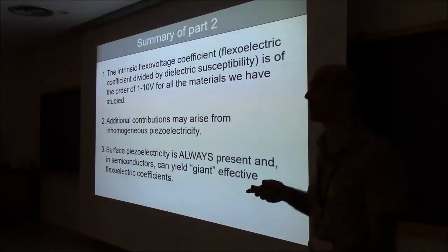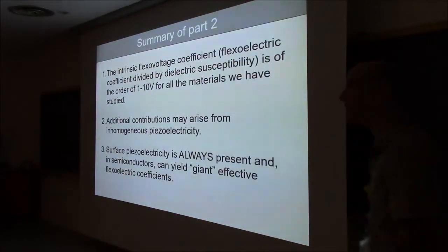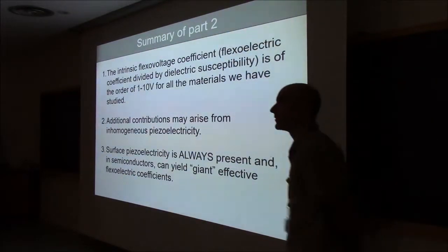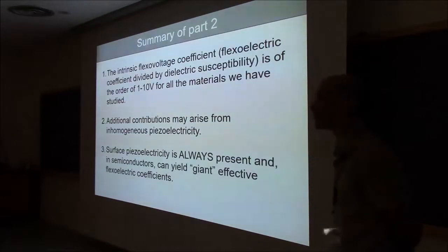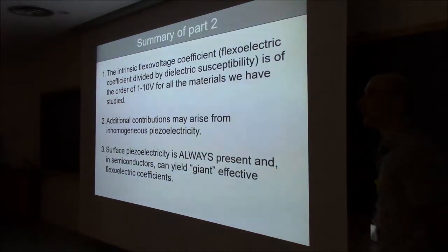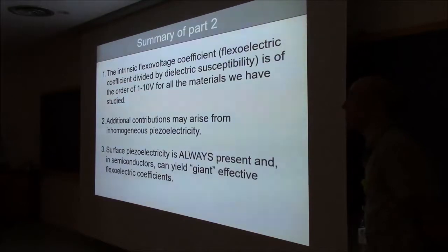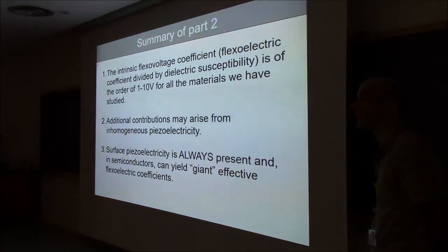Has the same been done for STO, like where you make oxygen vacancies to make it more conducting in the center? I have not done it, but there's no reason why it shouldn't work. In theory, you can just put it in the oven and see what happens. I mean, if it works for niobium-doped rutile, it should work for niobium-doped STO, and certainly for oxygen deficient STO as well.